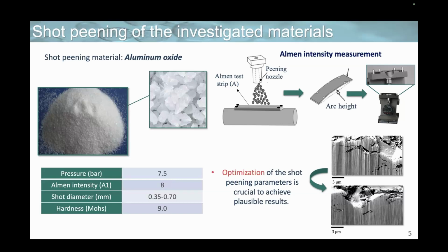It is very important to mention here that the shot peening procedure in terms of hydrogen embrittlement is not a straightforward process, and comprehensive optimization of parameters has to be conducted to achieve a plausible result. This you can see very well on these two pictures, where the first picture shows the stage at which we started. So we have a non-uniform shot peened layer, and we have the presence of deep cracks and a high percentage of surface defects. And only after several optimizations of the parameters, we managed to achieve what you can see on the second picture, and that is the mostly uniform shot peened layer with a small percentage of surface defects.